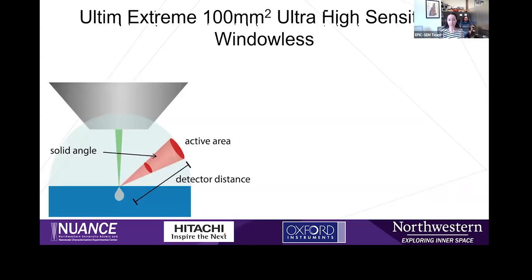So while this detector technically has a bit of a smaller area than our Ultimax, it actually has a larger solid angle because it's configured in a way that it can be much closer to your sample. So if you go back to this solid angle diagram, you can see that by just decreasing the distance to your sample, the area you need to collect the same amount of X-rays can be smaller.